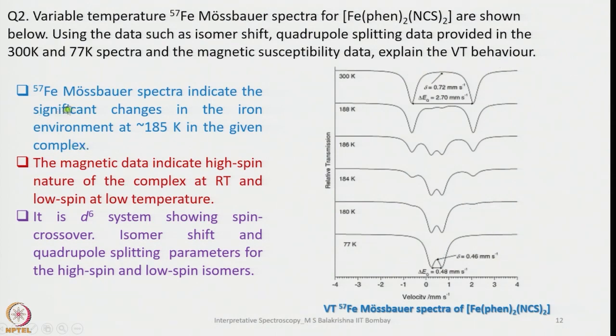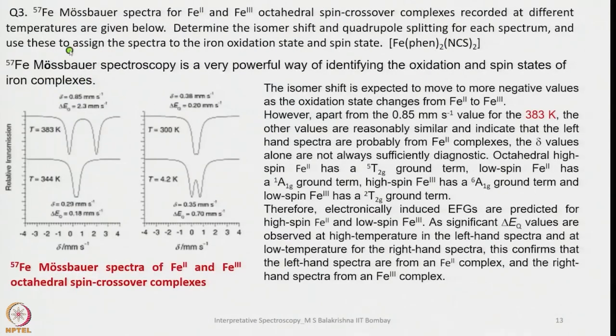So now, 57Fe Mössbauer spectra indicate significant changes in the iron environment at around 185 K, from 180 to 184 you can consider, it is significantly changing, these peaks are growing here. The magnetic data indicate the high spin nature of the complex at room temperature and low spin at low temperature. So it is a d6 system showing spin crossover. Isomer shift and quadrupole splitting parameters for the high spin and low spin isomers. This is another question now.